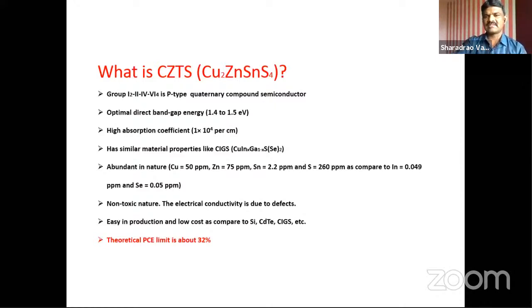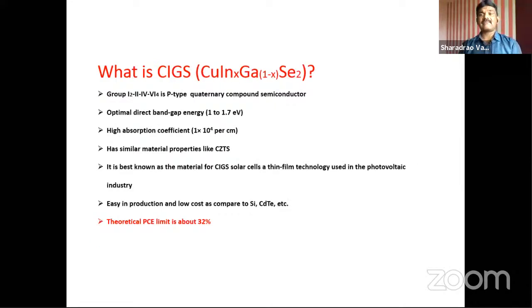The theoretical photo conversion efficiency of CZTS is about 32%, but unfortunately, it has not been achieved. The highest efficiency using CZTS type of material is recorded as 9 to 12% at laboratory scale. Now, the second advanced material, as far as the solar cell is concerned, is CIGS. CIGS means copper, indium, gallium, and selenium. It is also a quaternary compound semiconductor having a direct band gap in the range of 1 to 1.7 electron volt.